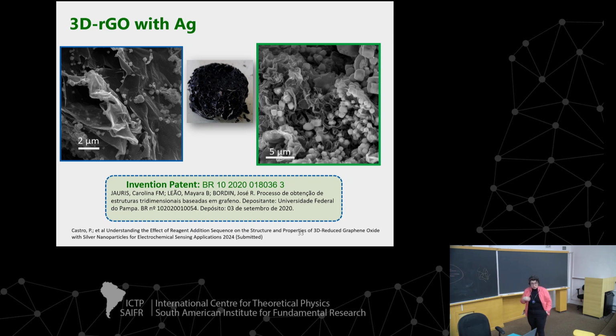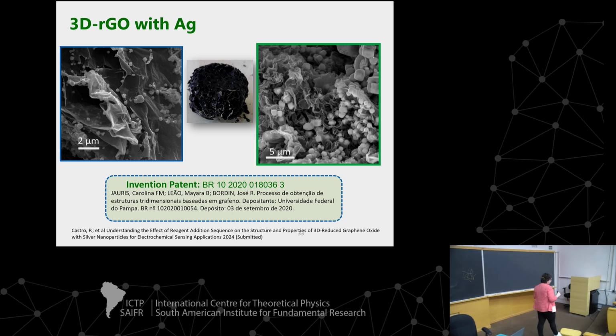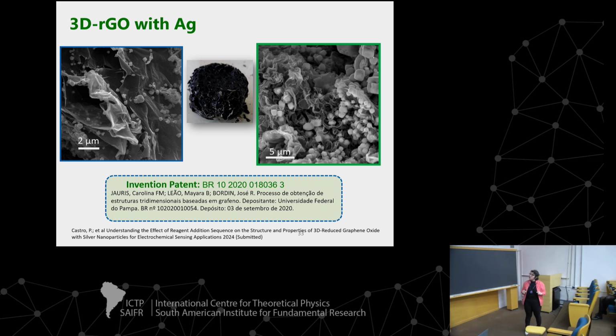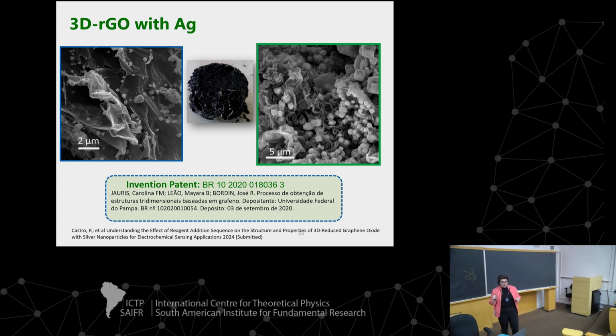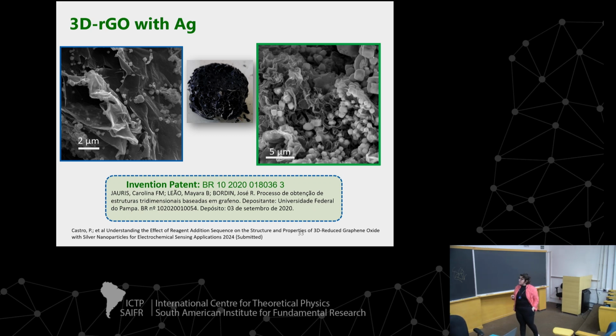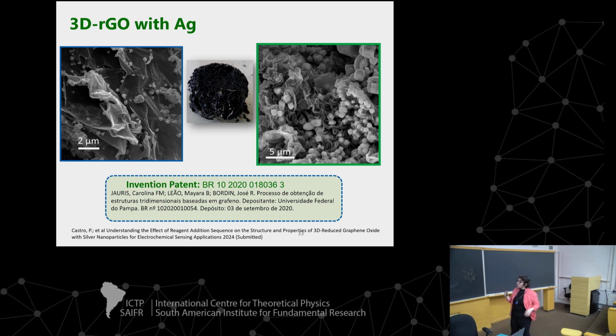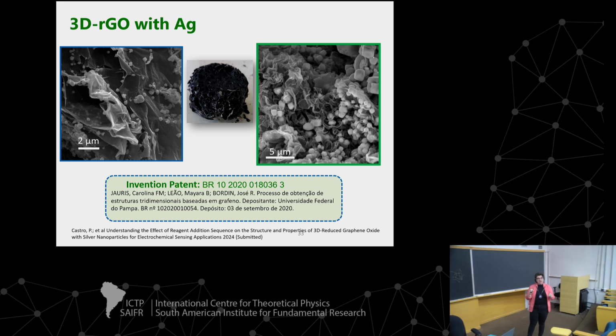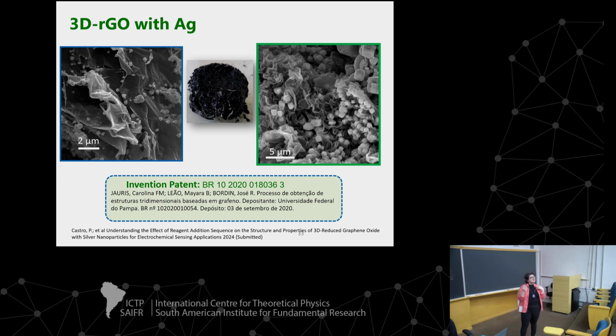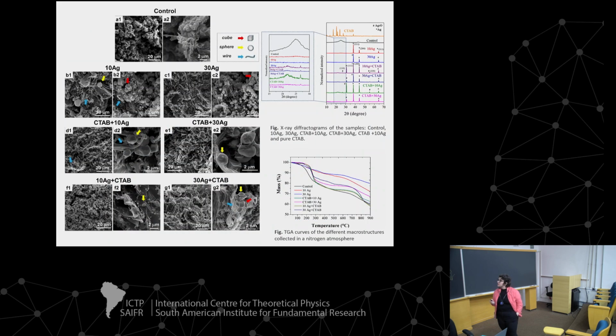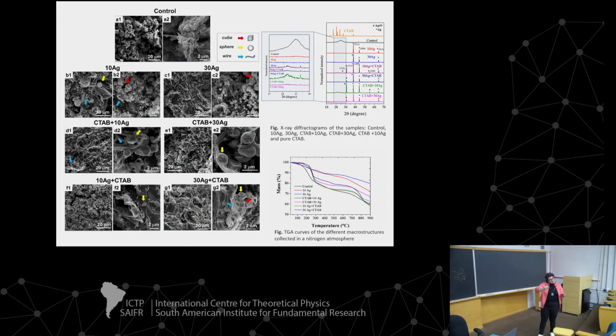Another system, to improve the different properties of these materials, we decorated these 3D graphene-based materials with nanoparticles. One of these nanoparticles was silver. Why silver? Silver is interesting for sensors, bactericidal, and for energy storage, and this is why we insert silver in this material. But the preliminary study was to try to understand what is the effect of the reagent addition sequence. If I add first a surfactant or first a metal, what can this change in my material structure, and what can this change in the properties of these materials? We only change the order of the sequence of adding the reactants.